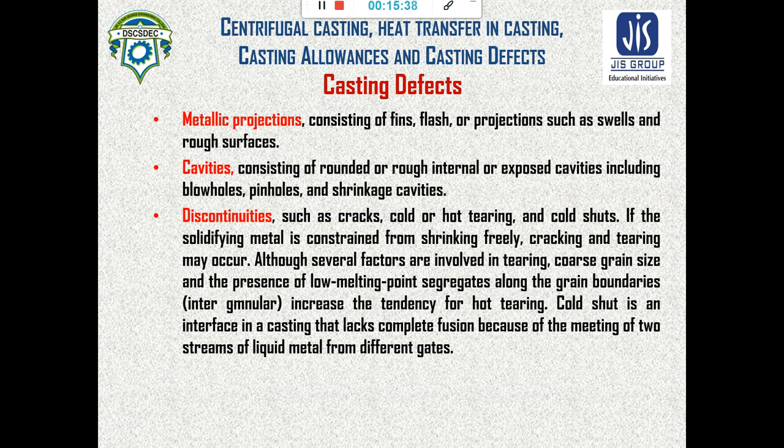If the solidifying material is constrained from shrinking freely, cracking and tearing may occur. Although there are several factors involved in tearing, coarse grain size and the presence of low melting point segregates along the grain boundaries, that means intergranular, increase the tendency for hot tearing.